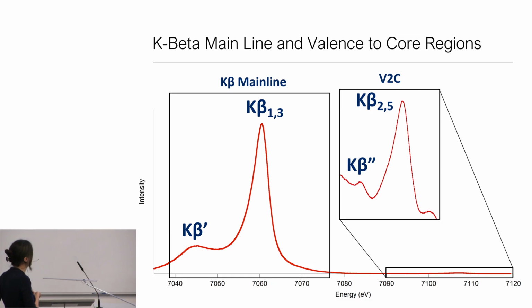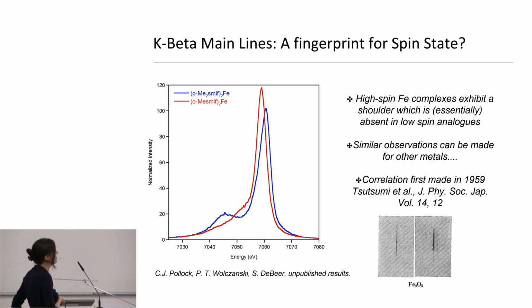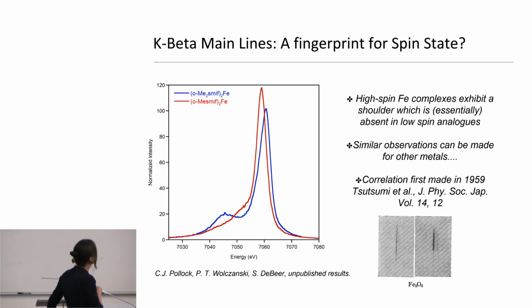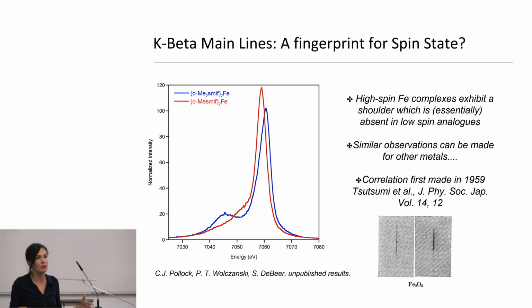So let's just talk about the types of experiments that these setups actually enable. So I already sort of hinted with the K-beta lines is that these are probes of spin state, and then we have our weak valence to core. Now, what's interesting about these K-beta mainlines is they're actually quite easy experiments to do. And if you look at a low spin shown in red versus an analogous high spin iron complex shown in blue, they have very distinct K-beta mainlines. And these are actually really easy measurements for us to do in-house. They're actually easy measurements to do in a dispersive and time-resolved way.